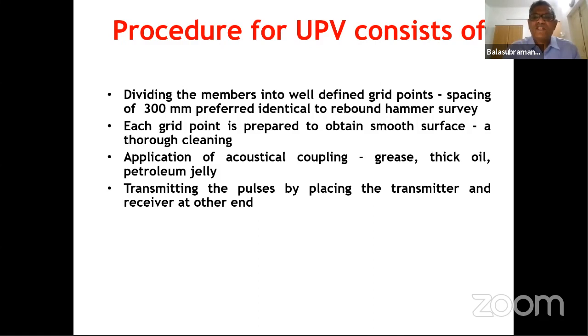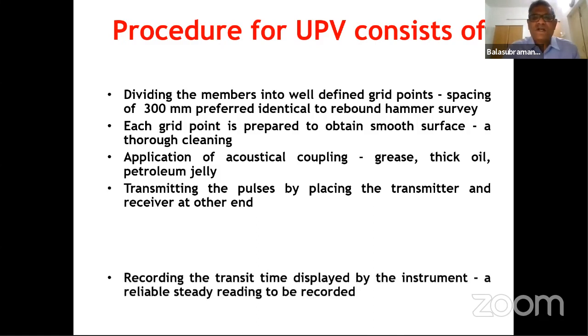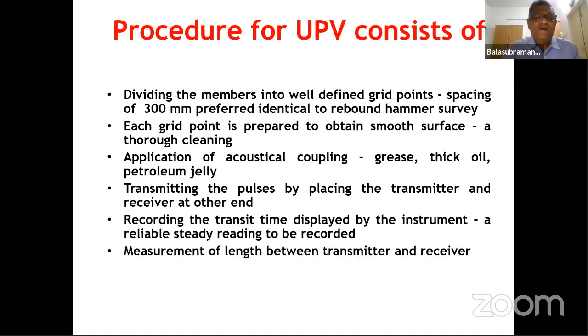And each grid point is to be prepared. It has to be smooth. And then we need to apply an acoustic couplant, like grease or something, between the transmitter and the receiver so that the pulse is properly transmitted. And the transit time is recorded in an instrument. Generally, people use Pundit. And then the velocity is calculated as L/T, that is, the distance between the two transducers divided by the time taken. So if the velocity is more, then the quality is more. That is, the time is less, the velocity is higher. So the integrity is much better.